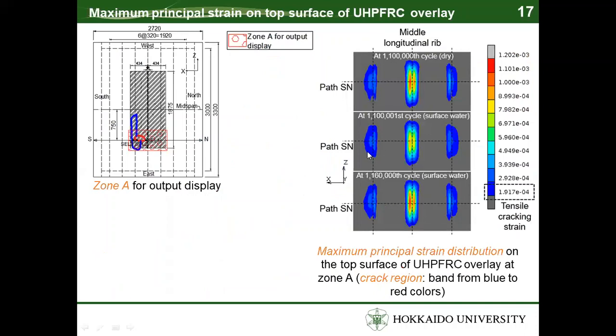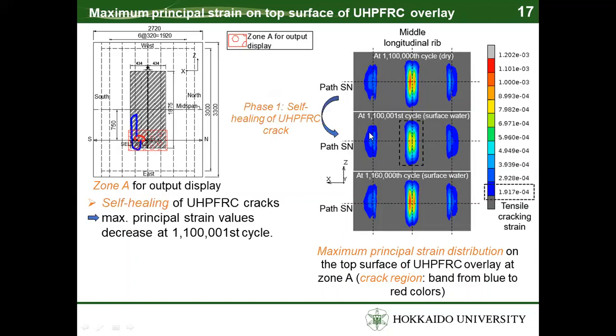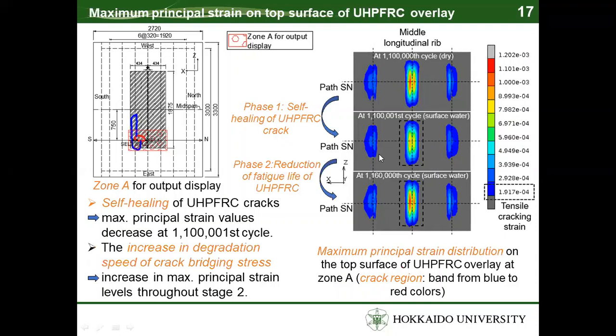This figure shows the maximum principal strain distribution on the top surface of UHPFRC overlay, zone A. The strain levels are shown by the bands from blue to red color. In phase 1, due to the self-healing of UHPFRC cracks, the maximum principal strain value decreased at this cycle. And after that, under moving wheel loading, due to the reductions of the fatigue life of UHPFRC, an increase in maximum principal strain level could be obtained throughout stage 2, as shown in this figure.